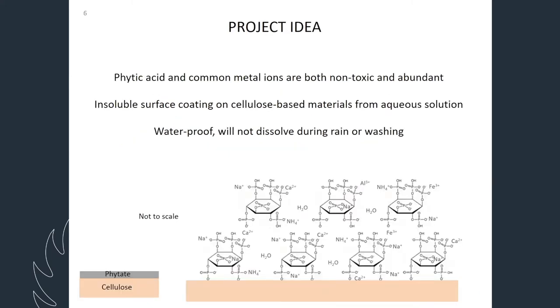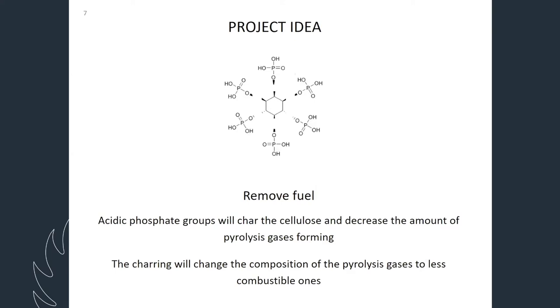So if we look then at our project idea, it's to take this phytic acid and common metal ions that are both non-toxic and abundant. We will form an insoluble surface coating on our material, cotton or wood, by dipping it in an aqueous solution of this phytate mixture. So this insoluble surface coating, which means it's insoluble, so it will be waterproof. It will not dissolve during rain or washing. So the picture there with this layer.